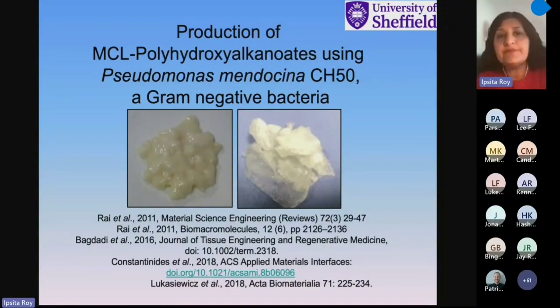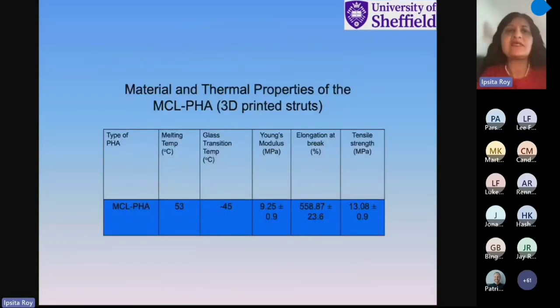I also produce the elastomeric ones, the medium chain length PHAs, and these, like I mentioned, are very, very different. The melting temperature is much lower, about 53. I won't read out all the properties, but will point out that the Young's modulus is only about 9 megapascal here, and the elongation at break, in contrast to the low value you saw earlier, is about 600 or 550%. So a really elastomeric polymer.